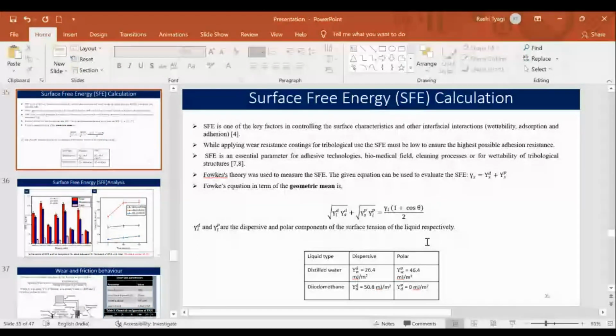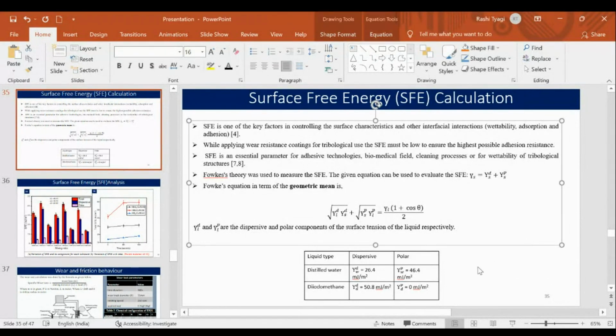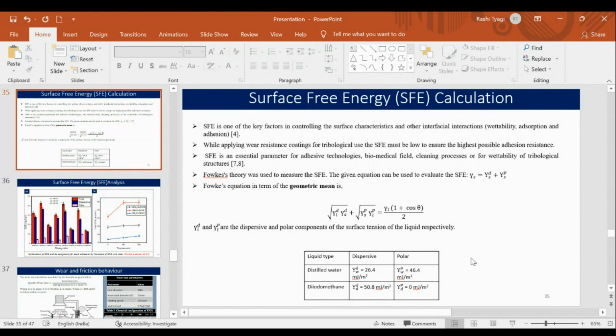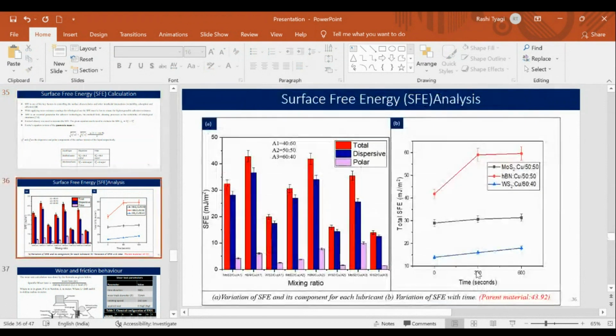I have already told you that intermolecular attraction forces take place. There are also adhesion forces and cohesion forces that will attract or repel the molecules. So we are using two liquids. The first one is water, for which we have already measured the contact angle. The second one is a dispersive liquid, diiodomethane, which has zero polar component, meaning it has only a dispersive component. So intermolecular forces can basically be measured by using these components. By using this formula, you can measure the surface free energy of the solid.